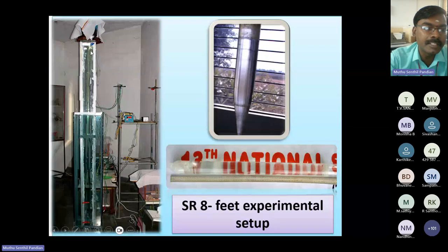So this is the schematic setup of this 8 feet SR setup. We mounted the seed crystal at the bottom of the glass sample here, and we maintain one temperature at the bottom portion and another temperature at the top portion for solvent evaporation. The total length is 8 feet, and we pour the solution from the top of the glass sample. When the crystal is growing from bottom to top, we also have to raise the level of the heating coil from bottom to top. As I mentioned, we have to maintain a uniform temperature between the crystal and the solution interface. So this much transparent large single crystal is possible by this SR method.